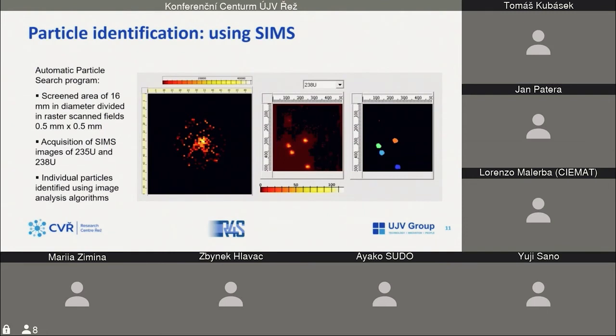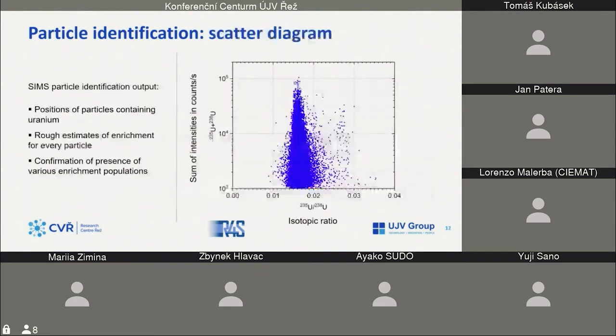So on the left image, you can see those dots represent a single field. As you can see, we inspected a circular area in this particular case. And on the right-hand side, you can see images of a single 500 micron by 500 micron field. You can see there 4 or 5 particles of uranium. And on the right-hand side, that image is after image analysis processing, where particles are identified by colors. So the outcome of this part of the analytic procedure are positions of particles containing uranium.